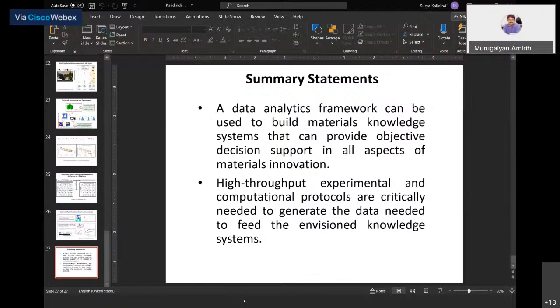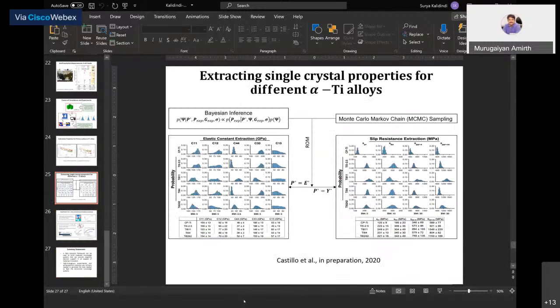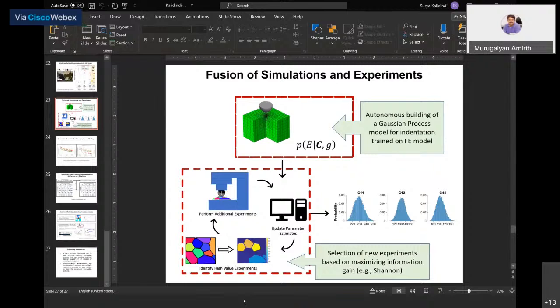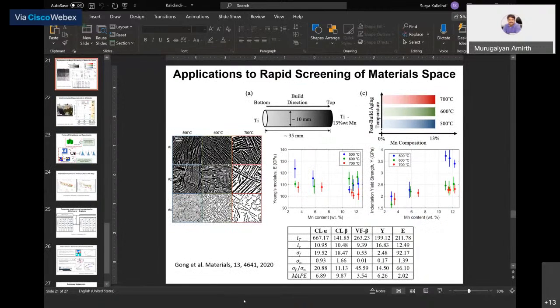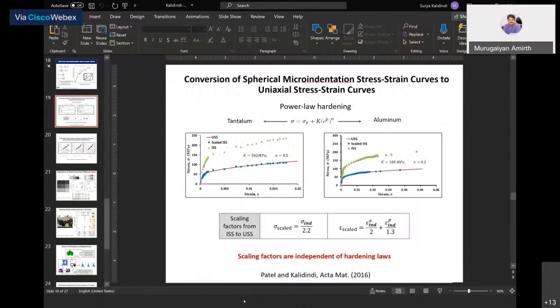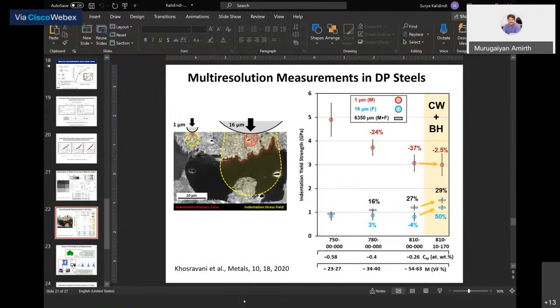So in the multi-resolution measurements you carried out, the role of interface, how do you capture that in the physics-based model? Because in DP steels, the interface boundaries are important in terms of predicting the properties, generating mobile dislocations, for example. If you're doing a highly localized measurement, the interface information is missing, I suppose, right? And how do you capture that?